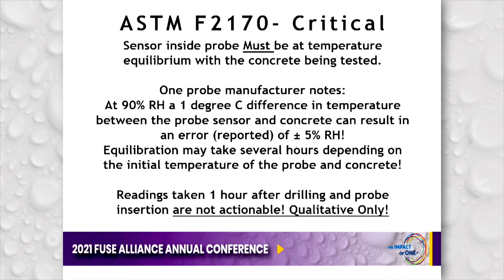That is not actionable data. It may be qualitative, but it is not actionable. And I'll accept that if you're installing a highly sensitive floor that requires 75% relative humidity, and 1 hour into your test, you're reading 90% on one of these probes, I can promise it's not going to come down to 75. But again, it's actually qualitative, not quantitative.